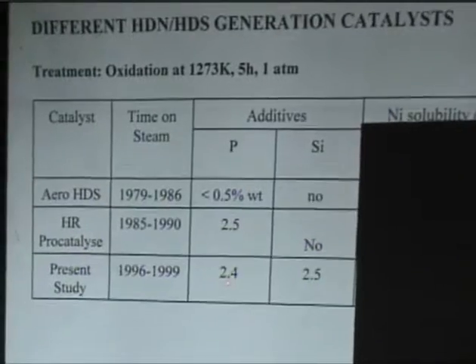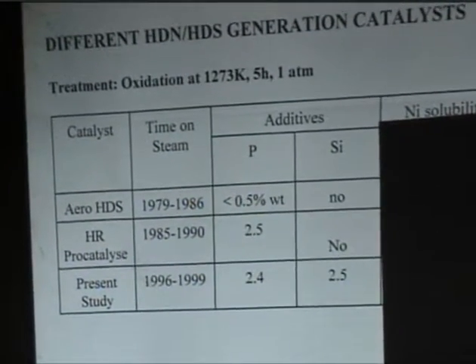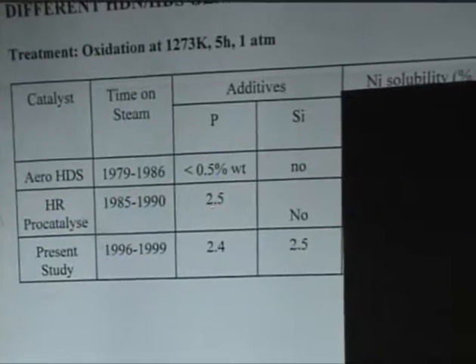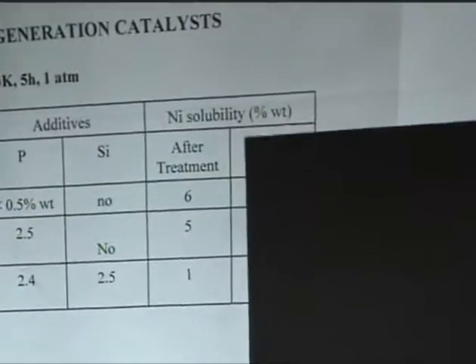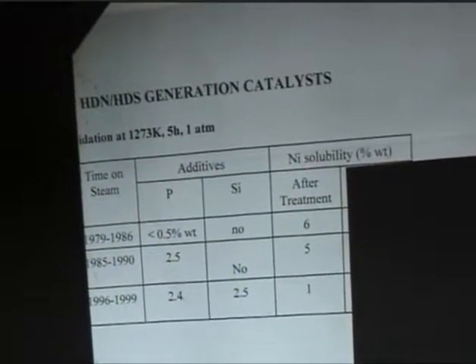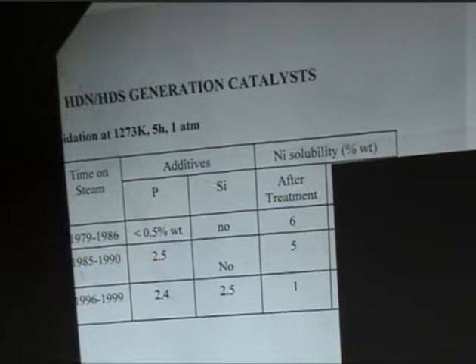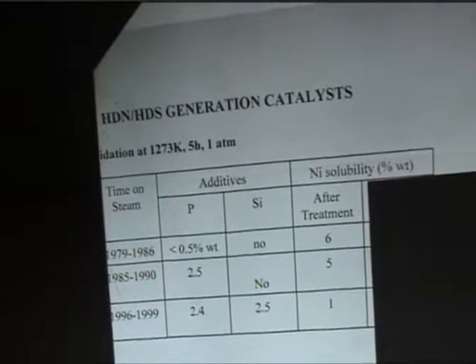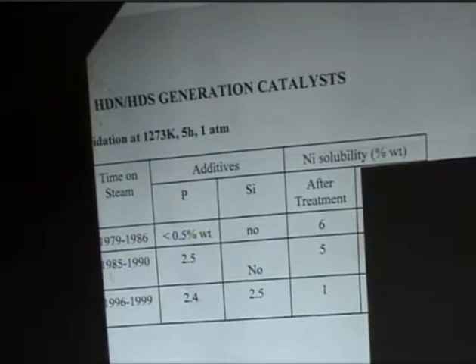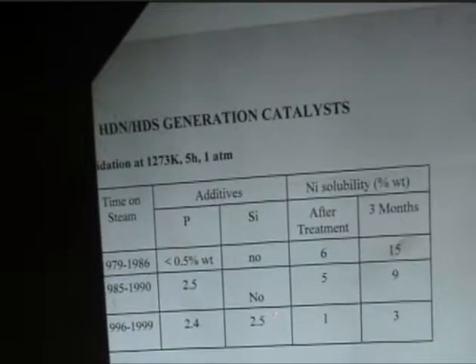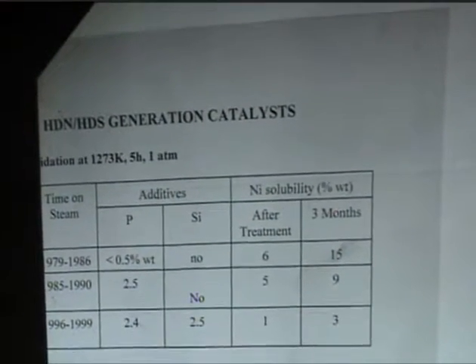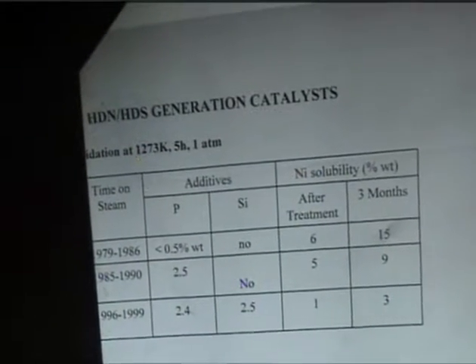All samples were packed under argon after being discharged from the reactor unit. The catalyst of this study contains silicon and phosphorus, whereas the Aero HDS contains almost no additives, and the HR Procatalyse contains only phosphorus as an additive. We have taken the solubility of nickel for comparison, since nickel is a very toxic element. As you can see, as the amount of additives is reduced, the solubility of nickel increases. And after 3 months in the ground, we have observed the same effect. As the amount of additives decreases, the solubility level of nickel increases, even at over 1000 Kelvin.